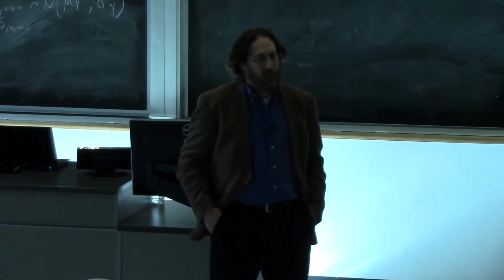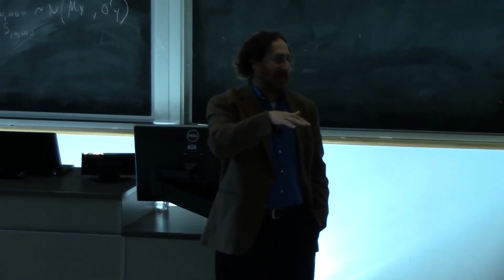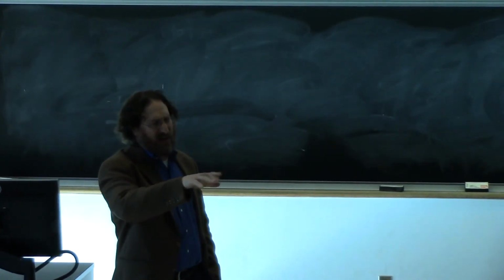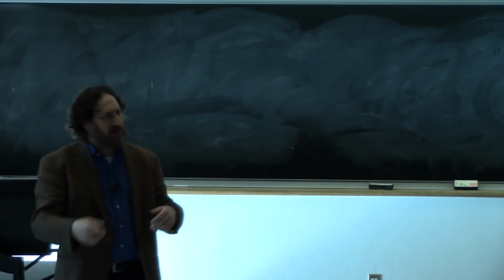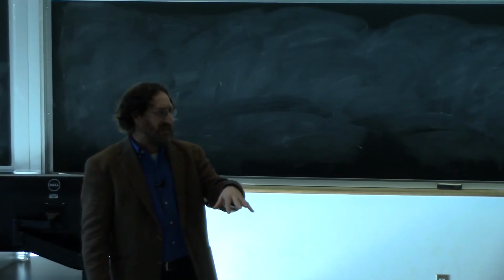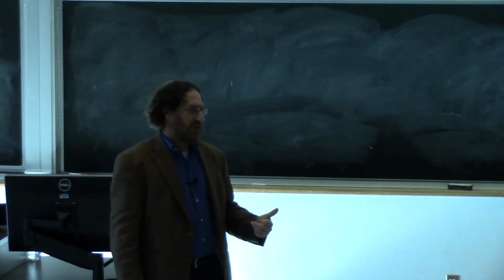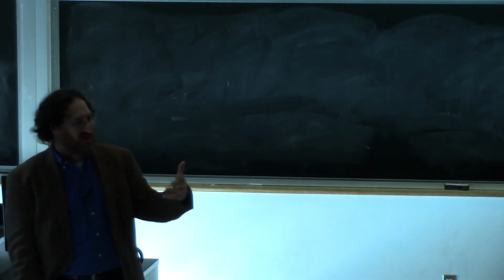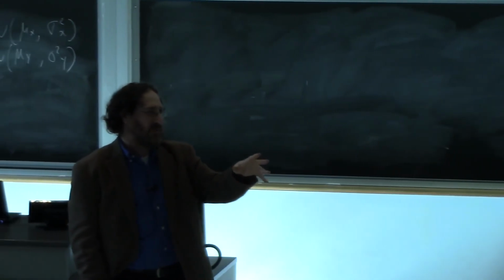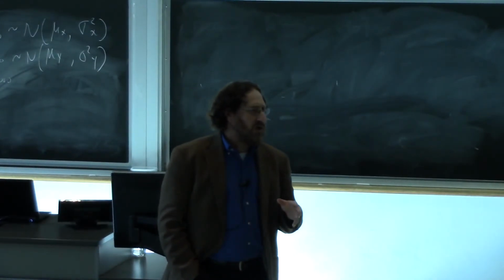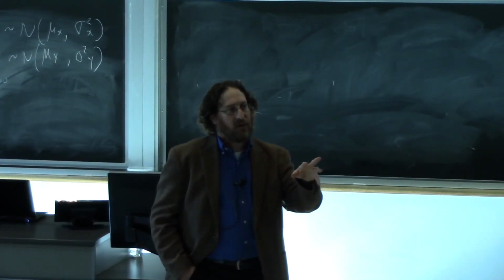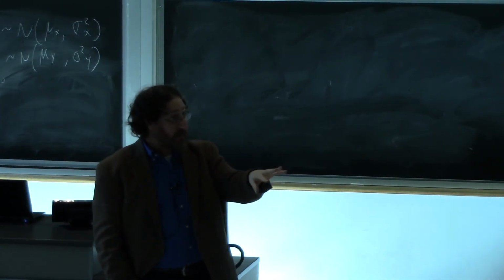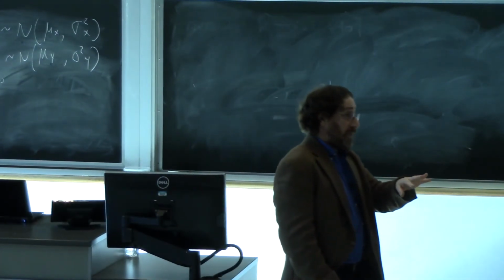Now, one of the things that happens is that when this lithium plates, a lot of times it gets isolated electrically, because you have these insulating layers. So if it's isolated in that way, it's hard to get it back into the equation, right? But the other thing is that once you start nucleating it, it's also happier plating, so your local potentials change. So I can't think of a scenario necessarily where just the simple material itself would fix it. But I could certainly think of control approaches where you could use it.